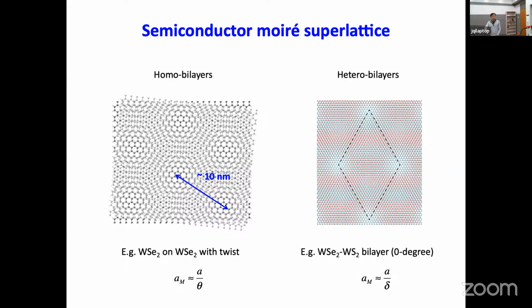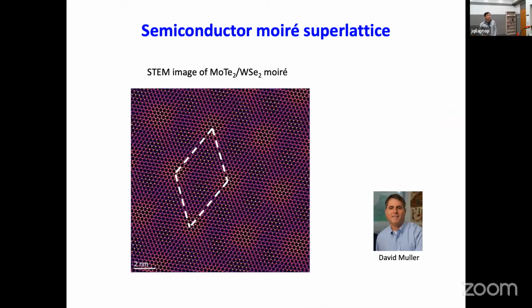Okay, and the difference here is that the Moiré period depends not on the twist angle, but on the lattice mismatch between the two materials, which I denote as delta. All right, so these are the two ways, and I'll mainly focus on the second way here because it's relatively insensitive to the twist angles. That's something that we like, and you can really see it in a TEM microscope.